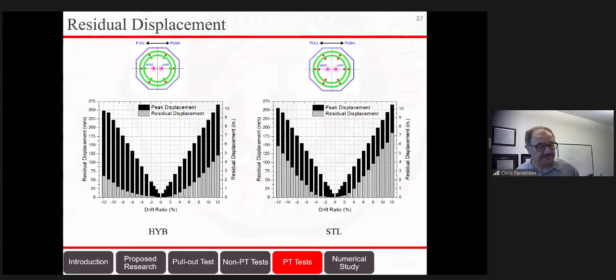How about the residual displacement? Well, the residual displacement was reduced definitely from the previous 2 tests. And you can see it here. On the left is the hybrid column, and on the right is the steel column. At 3% drift, the residual displacement of the hybrid was 6 millimeters, and the residual displacement of the steel was 8 millimeters. At 6% drift ratio, which is again a very high drift ratio, the hybrid was 23 millimeters and the steel was 48 millimeters. So even though both were reduced, the steel still had double the residual drift than the hybrid.